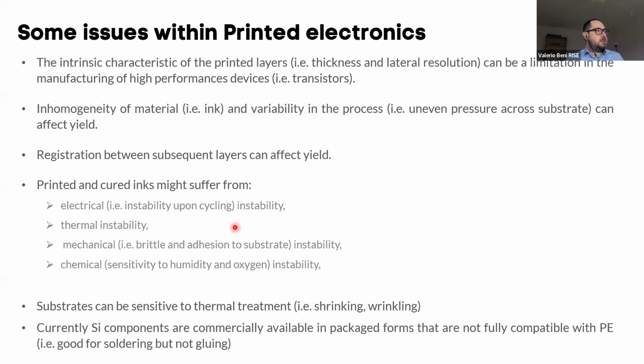Inhomogeneity of the materials and the variability in the process can actually affect the yield. So you might create a not uniformly reproducible device on a larger area, or you could have defects. Since this is a layer by layer process, registration between the different layers is actually very important. It could affect the yield, and this could be affected by the process in itself, but also by the material.